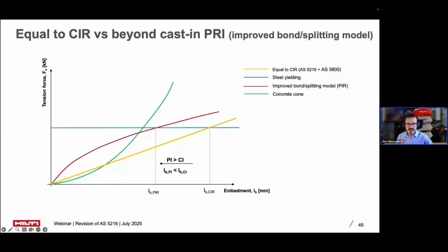However, reduced embeddment depth creates a potential for concrete cone failure, which must be checked in the new design method. The equal to cast-in approach embeds so deeply that concrete cone failure is unlikely, but the improved method requires verification that concrete cone failure doesn't govern the design.